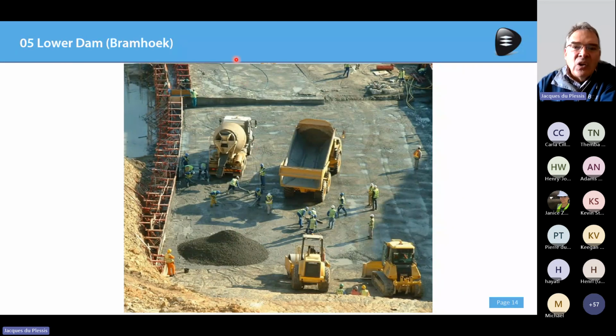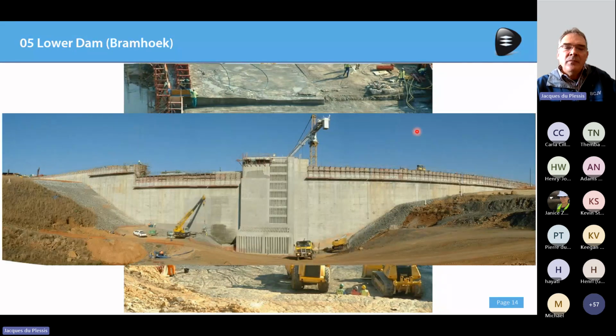And because you're doing it in long sections up to a meter height, you induce joints in the RCC, otherwise it will crack everywhere. And there where you induce the joint, you don't see the joints here yet, you install a water stop on the upstream side. So you actually tell it where to crack, and then you just seal that crack. So completely different to the rockfill dam at the top.